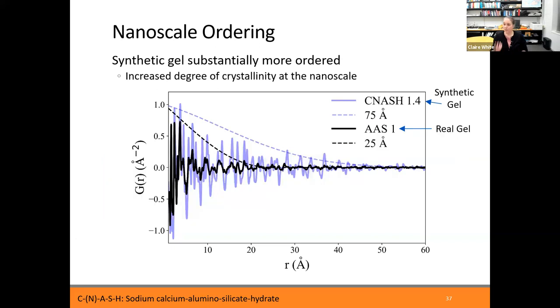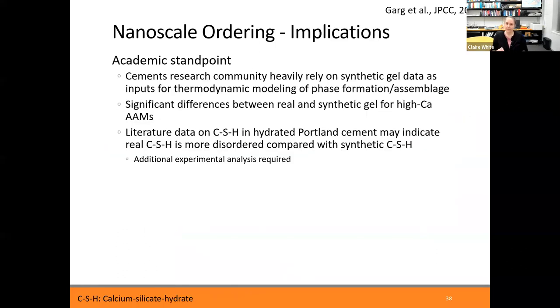A similar argument could potentially be the case here, whereby the more disordered gel, this real gel, is less thermodynamically stable compared to the synthetic gel. So we need to be careful about using thermodynamic data, and specifically things like solubility product for the synthetic gels, for inputs to thermodynamic modeling, because essentially the community uses a lot of thermodynamic modeling to predict phase composition in the concrete. And the thermodynamic data for the gels comes from these synthetic gels.